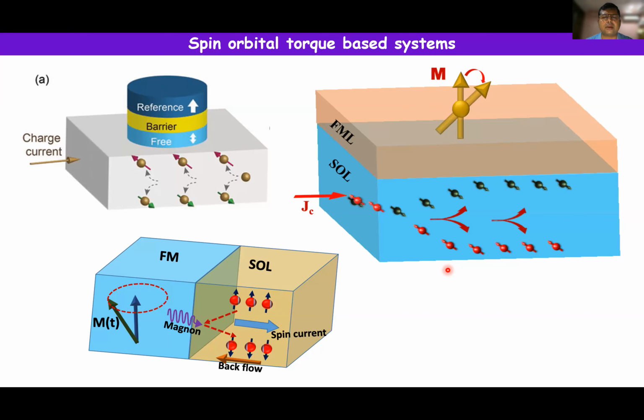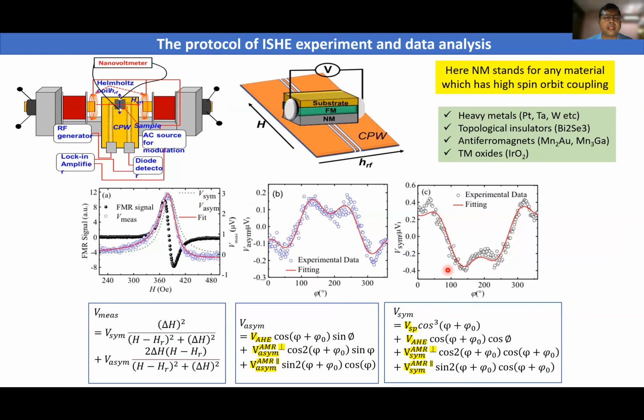Yeah. So now let's talk about these different materials for spin to charge conversion. As I said, the primary requirement is high spin-orbit coupling. Now, in our group, we mostly look at it through the inverse spin Hall effect. So basically, the protocol is you put your sample flip-chip on the coplanar waveguide, and you pass a high frequency microwave field. You basically pump energy to it. Now it generates a spin current which goes through the ferromagnet to the high spin-orbit coupling material. Here it's called non-magnet. And then you develop a voltage which you can measure, here using a nanovoltmeter.